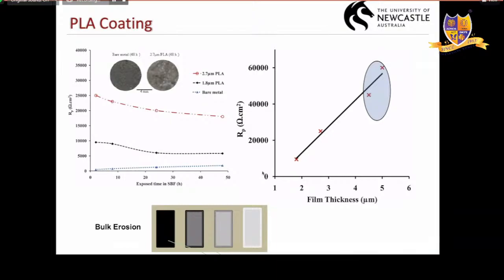These are some of the results of a spin coating of polylactic acid. Here, as the thickness of the coating increased, the resistance also increased. But very high resistance also was not desirable because of the degradation mechanism of polymers. They undergo a process called bulk erosion. It's not the surface erosion; it's a bulk erosion. So since it's a bulk erosion, the higher the thickness, the more permeation gets into it, and the bulging of the coating occurs. So we have to optimize the thickness of the coating. Here we found around 2 to 3 microns were good enough to withstand the resistance, and also to provide some long-term protection.